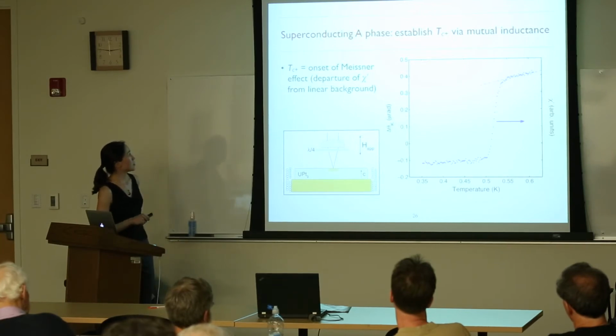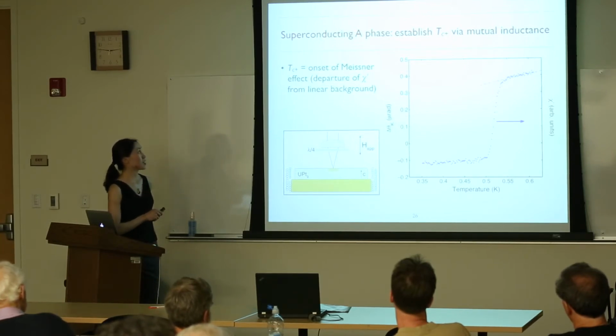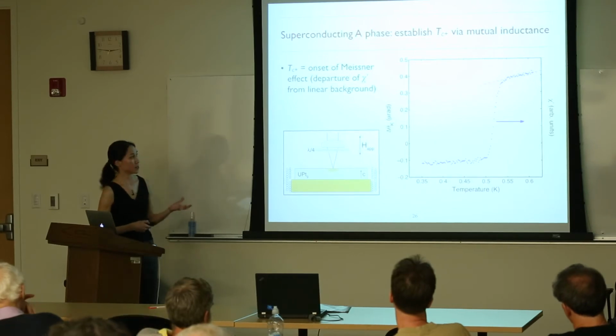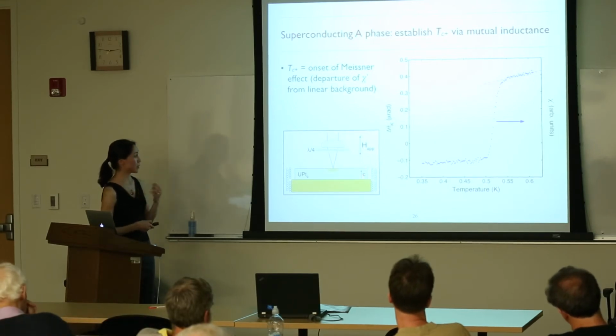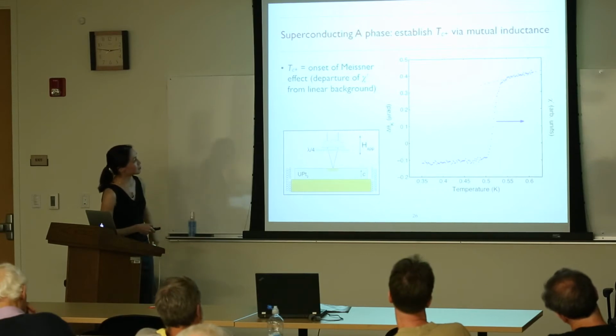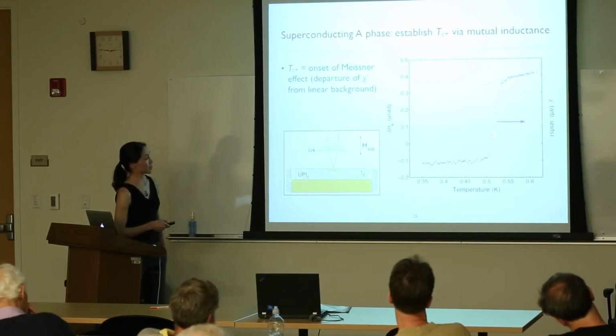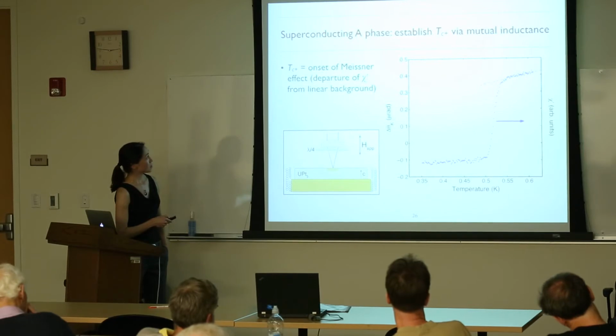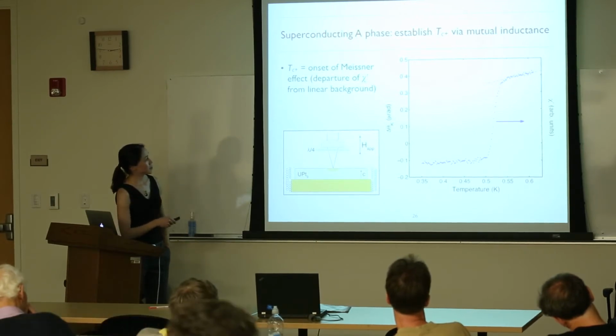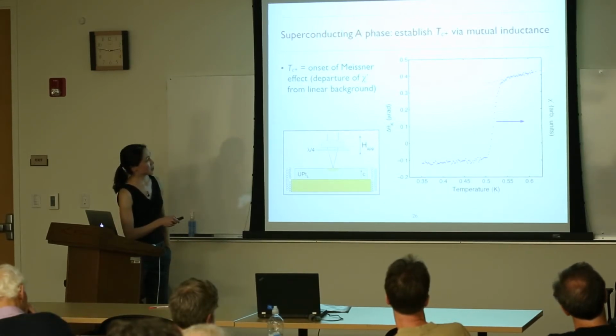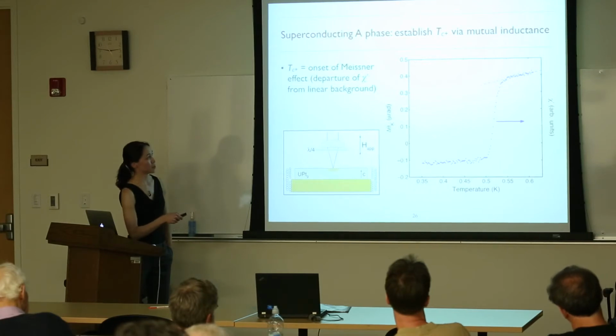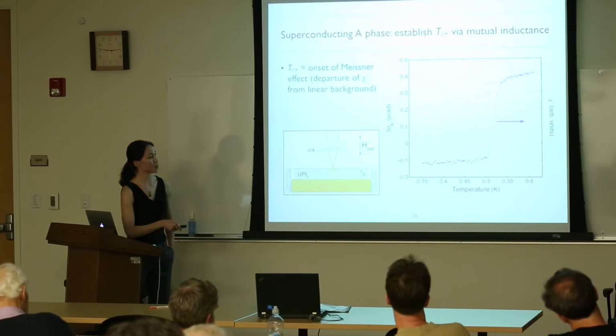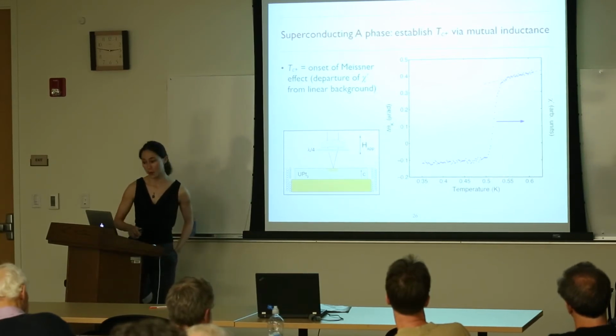So again, the first thing is to look for superconductivity in general, which is going to tell us TC+. And that's going to rely on using our mutual inductance little setup here. This is what you get as a function of temperature. Basically what we do is we identify TC+ with the onset of the Meissner signal, which is where your mutual inductance, or the real part, starts deviating from your linear normal state background. So it's right about here, which is right about 550 millikelvin, as we would hope.